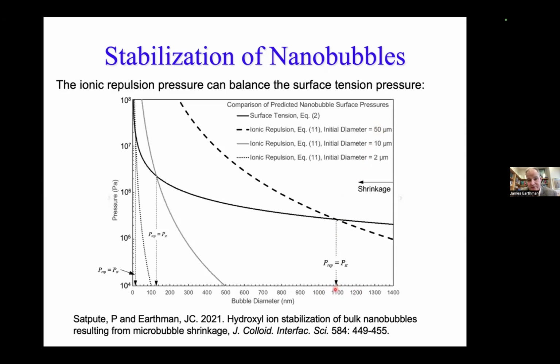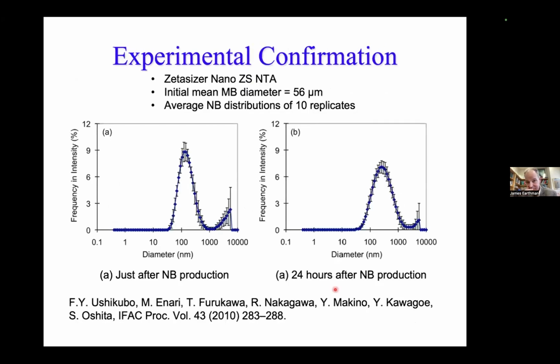Okay? So first thing I wanted to do when we saw this is see if there was any experimental data to confirm this, and it turns out there is. This is some data from a group in Japan who did Zetasizer Nano measurements. This is a light scattering technique. They could measure the zeta potential, but they could also measure the size of the nanobubbles with this instrument. And it's a light scattering method. It uses a CCD camera. And they measured the distribution of nanobubbles produced by a large, diverse microbubble distribution. So they would start out making microbubbles, they wait for the microbubbles to shrink, and then they would make these measurements of the nanobubbles. Okay, and these are the average of 10 replicates for them.